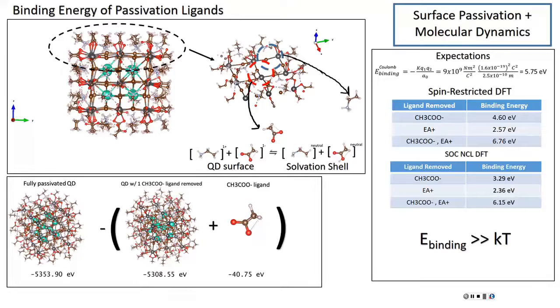I see. So the perovskite itself is neutral, right? Yes. And your ligand is 1 plus and 1 minus. A periodic, three-dimensional crystal is neutral. But if you cut surfaces, you can get an excess of anions or an excess of cations. The number of positive lead, negative bromine, and positive cesium are not really equal to each other because of this reason. When you cut the surface, you might have a surface enriched by cations or by anions. So basically all the bromides or halides that would be popping out of the surface aren't there anymore, and they're replaced by ligands.